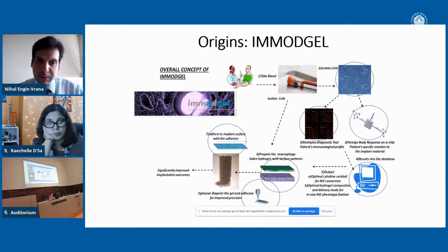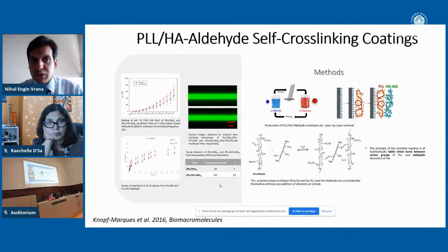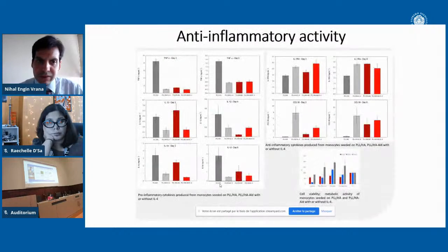And when we were looking at the potential adhesives, we were looking at layer by layer structures. And in these structures, we were looking at how we can cross-link them, whether we can have self-cross-linking structures with aldehyde groups, so that we can attach these hydrogels. This was one of the formulations, which is based on PLL and HA aldehyde. And one thing we have started to notice is that we were loading anti-inflammatory molecules inside these to have an effect on the macrophages. These are the cytokine secretions by primary macrophages in the presence of these coatings. And once we add interleukin-4, which is an anti-inflammatory cytokine, what kind of reaction we get.